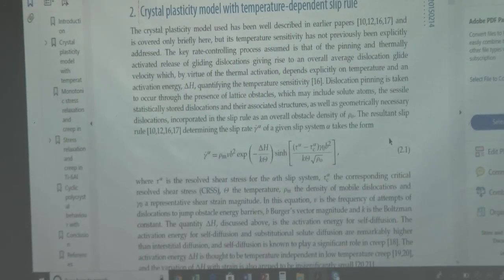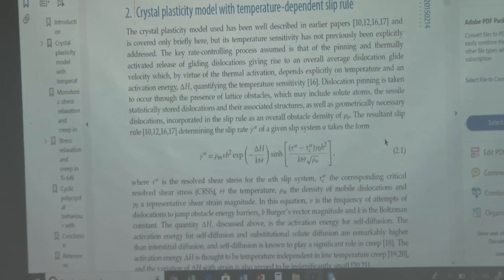You see what I'm saying, right? In order for a shear strain to happen, you have to have a difference in shear stress. That's what I tried to do here, sigma 1, sigma 2, to produce the d epsilon. So here to produce the d gamma, you have a d tau. The d tau is equal to tau minus tau critical. So don't make this mathematics too hard, as hard as Ramanujan's mathematics. It's not anything close to it. It is the same way, sigma yield and sigma. Tau is equal to sigma divided by 2.